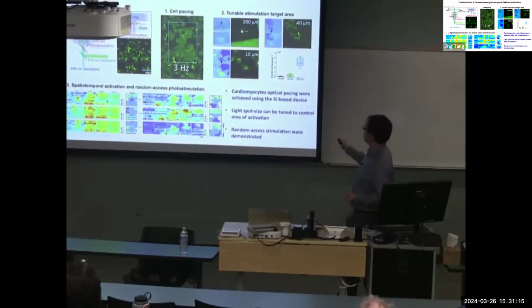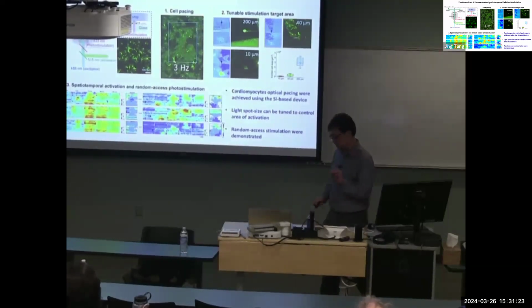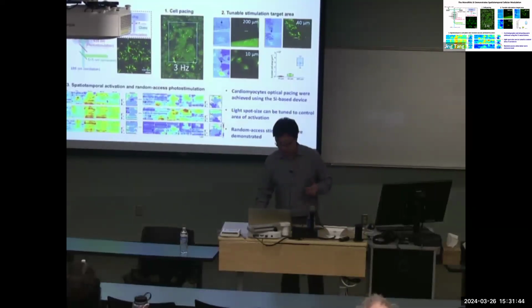For example, you can change the light spot size so that you can control many cells or just down to a single one or two cells. You can actually achieve subcellular manipulation as well. Additionally, we can change the location. For example, you start stimulation here or here, and your initiation point, the bioelectric initiation in that cardiomyocyte monolayer, is also different. You can use either membrane voltage dye or calcium imaging dye to verify that.